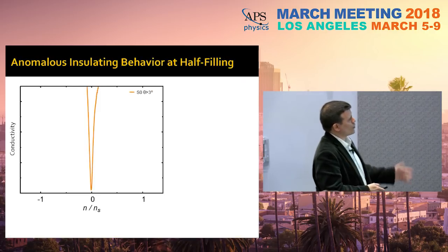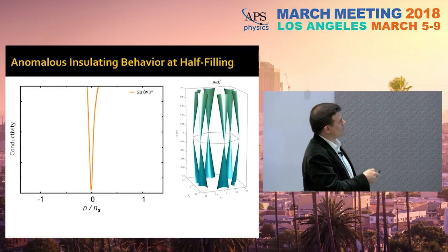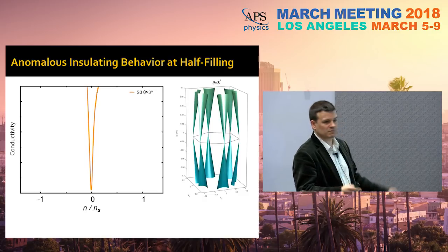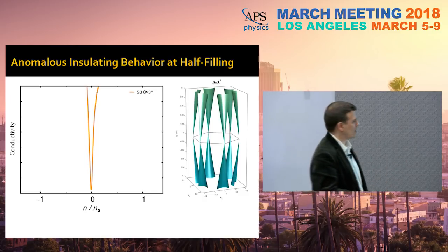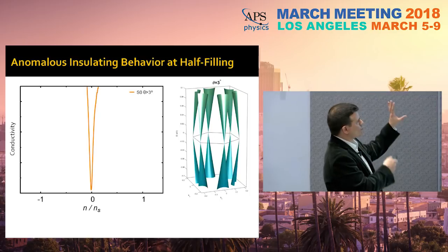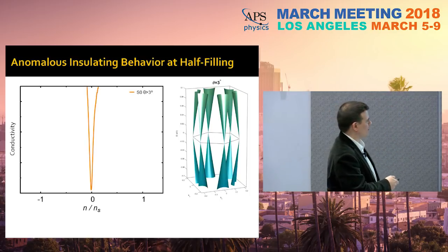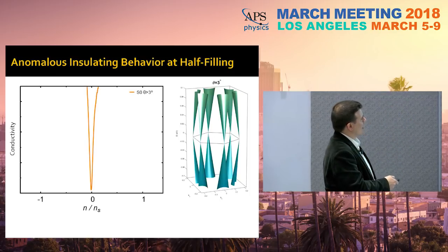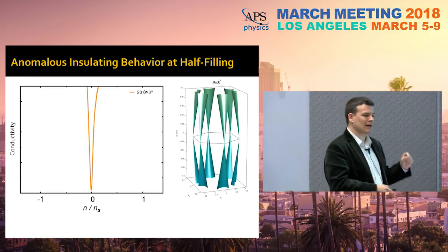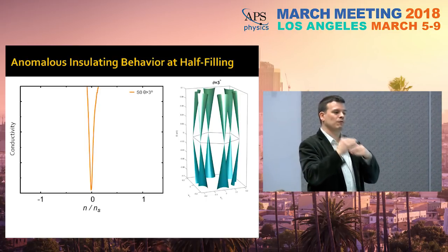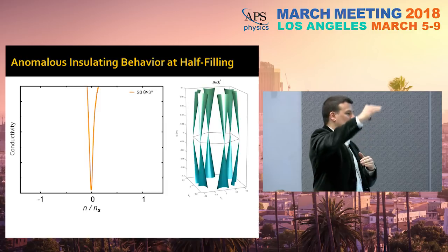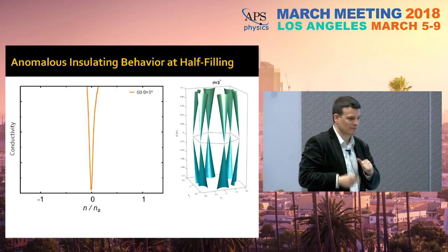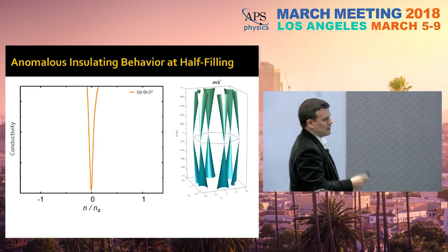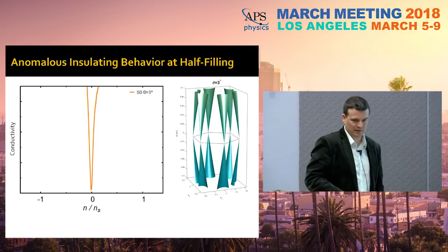Now let's see what happens when you have these twisted bilayers as we reduce the angle of rotation. So I showed you first for 3 degrees. Again, this is just this V shape, which is representative of graphene. Okay? That's all that happens. I'm showing conductivity. I'll show real axis with units in a moment, in the next slide. Here I'm showing conductivity as a function of density. I am normalizing the density by the full density of electrons that can fit in that flat band. Okay? So one means I'm putting as many electrons as fit in this band.